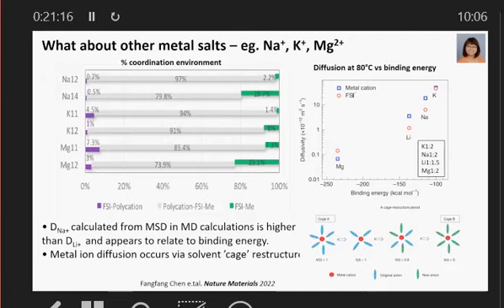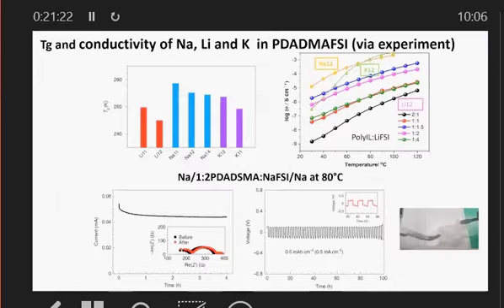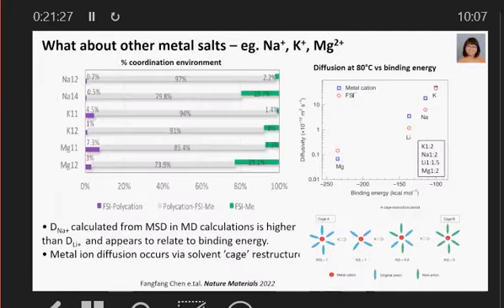And what she also found in that work was that, if you think about normal solvents or normal polymers, you think about ion dynamics being related to vehicular motion. People talk about hopping motion. What she found very clearly in this work, and also is true in the ionic liquids work, is that the transport of the ion occurs through a rearrangement of the solvation cage. So you go maybe from having, say, 6 coordination in a certain time step, you might have 4, and then new FSI, new coordination environments join, and then ultimately you've changed the cage you're in from A to B. And that's how the diffusion occurs, through this structural rearrangement of the coordination environment.